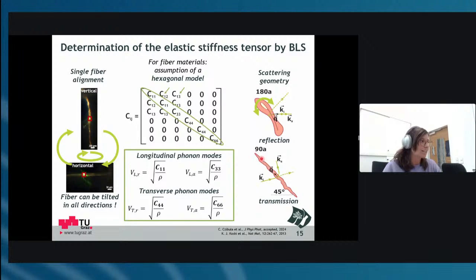And then there is another one, it's 90A, and this is a transmissive geometry. Here I come with the incident light from one side, and I collect my scattered light on the other side. Here we have a 90-degree angle, and the fiber is oriented at 45 degrees. And as you can see, with this kind of scattering geometry I can measure the axial direction of the fiber. That would only be possible in 180 if I check cross sections of the fiber. So there would again be sample preparation necessary, and then whatever mess comes along with it. So this 90A is very nice to really get the axial direction without doing anything to the fiber. And it's a transmissive mode.